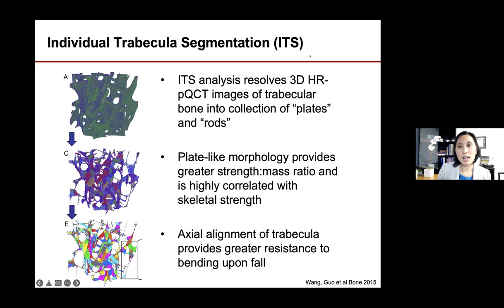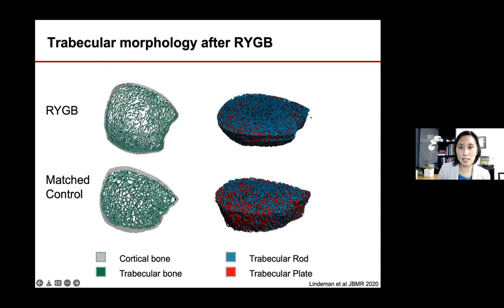And then using the more sophisticated individual trabecular segmentation analysis that again was introduced by Dr. Kazakia, we were able to look at trabecular morphology. And just as a reminder, plate-like morphology appears to provide greater strength-to-mass ratio than rod-like morphology and is highly correlated with skeletal strength. And furthermore, the axial alignment or orientation of the trabeculae appears to provide greater resistance, especially upon compression or bending upon a fall. And so what we found was, here you have an HR-pQCT cross-sectional image of a gastric bypass patient, and the age, weight, gender, and menopause status matched control.